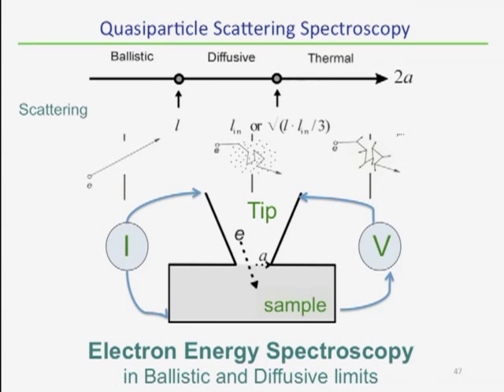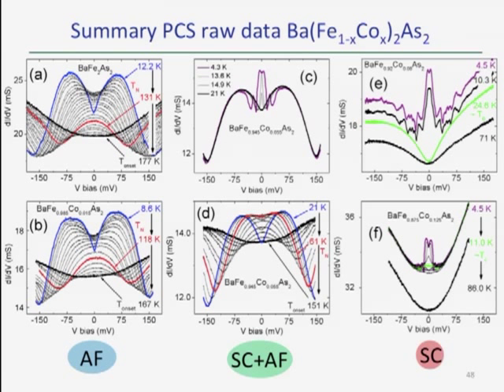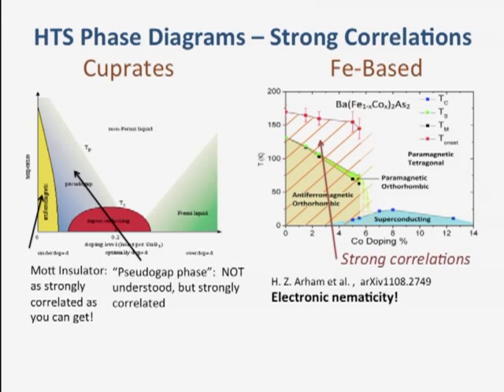What we found in the last few years is, in fact, for instance, this material, an iron-based superconductor. This is cobalt substituted for the iron in something called the 1-2-2, barium iron 2 arsenic 2. And we see this intense excess conductance that exists in certain places. That intense excess conductance in this point contact exists where other people have measured something called nematicity. So we found this easy way to find that, in fact, there are strong correlations that exist there, and we could measure them directly with this measurement technique that we thought was old, but is being applied to something that's never been applied to before.